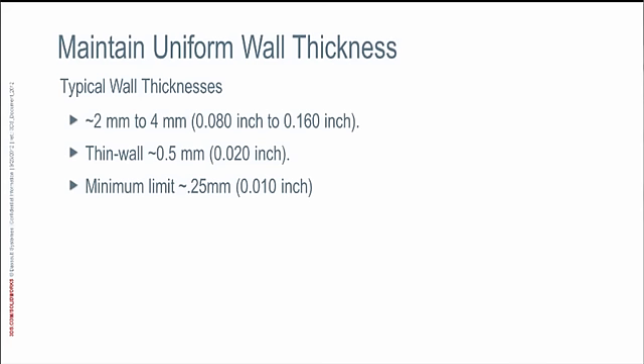On the opposite end, thin-walled injection molding — these parts might be down in the range of a half a millimeter or about 20 thousandths of an inch thick. The minimum limit is somewhere around a quarter of a millimeter or 10 thousandths of an inch. You might actually be able to injection mold applications less than 10 thousandths of an inch, but the flow lengths would not be very long, and injection times would be extremely fast — on the order of maybe 0.1 to 0.2 seconds.